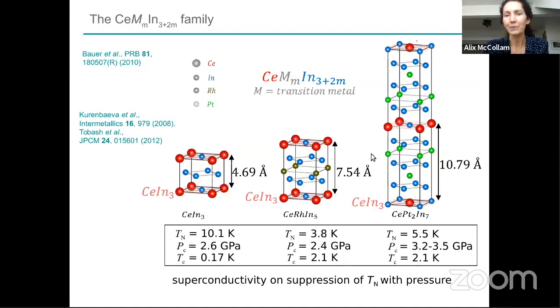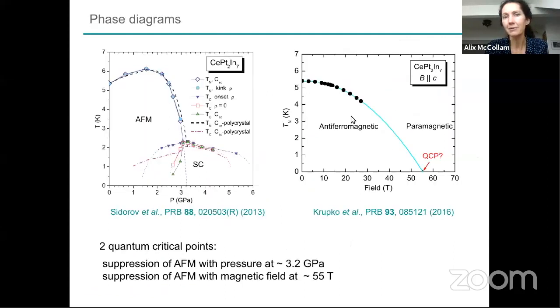The experimental difficulty is that these samples are little platelets. They're extremely thin along one direction, and we don't actually see very much signal when we try to measure in the field in the plane. So our strongest signals, particularly for the quantum oscillations, which is what we've been focusing on up to now, have been with field parallel to C. So I can't really say too much more about what it looks like with B parallel to the plane. We just haven't done the measurements along there. Thank you.